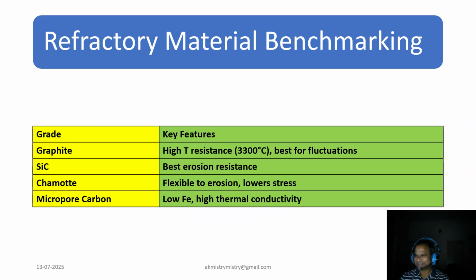Now coming to a slide where a lot of data is shown as a refractory material benchmarking activity. The material science shapes performance, as we all know. Graphite shines in fluctuation zones, resisting up to 3300 degrees centigrade. Silicon carbide defends against erosion. Chamotte adds flexibility, absorbing stress and wear. Micropore, low iron, and high thermal conductivity make it ideal for heat heavy zones where heat loads are high. Selecting the right material for the right zone keeps the entire system in harmony. And apart from that, the operation experts also try to find out how to adopt the operational discipline to derive these design outcomes.